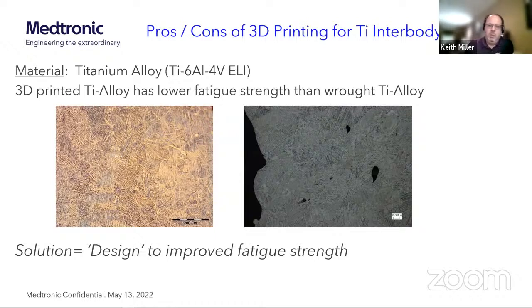So I'm really going to talk about pros and cons of 3D printing for titanium interbody devices, because really all we use at Spine here is titanium alloy. We don't use different materials, we just use that one. And if you just look at the material, the one thing to note is basically 3D printed titanium alloy has lower fatigue strength than wrought titanium. The way we design around that is we basically make the walls thicker. We just make things stronger to accommodate the fact that the material is a little bit weaker.